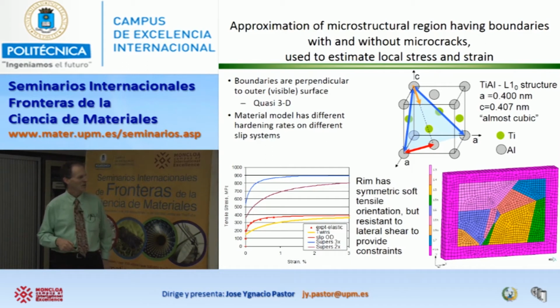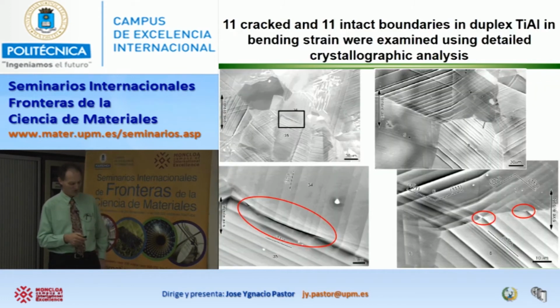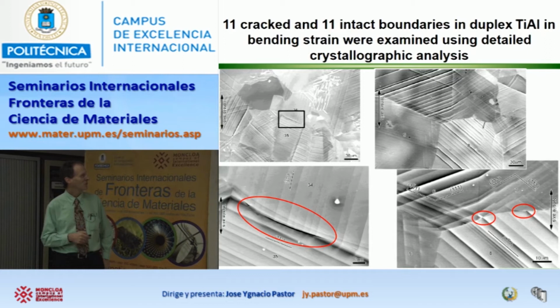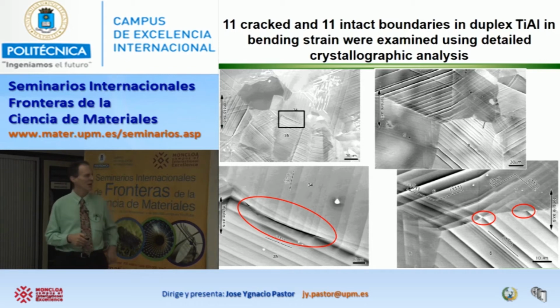So we wanted to simulate some microstructures and figure out why some of the grain boundaries cracked and why others did not, and if we could make sense out of that. So here's some examples of some cracks in a grain boundary. First of all, these lines that you see here, not all of them, but most of them, are mechanical twins, very thin mechanical twins. This boundary here shows a crack that's quite apparent. Here's another boundary right here, which has some somewhat smaller microcracks that have developed.